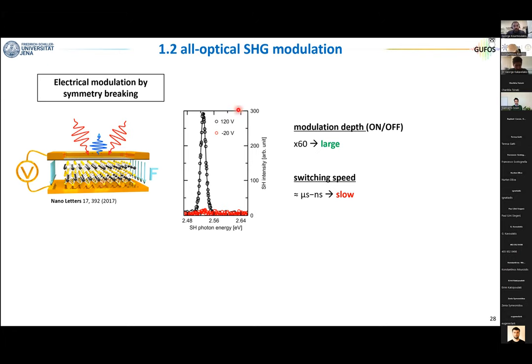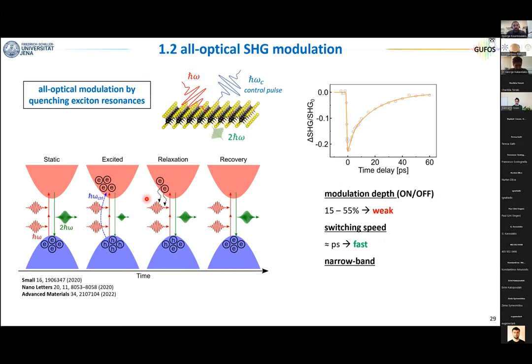So now you see that as a function of gate voltage, you have a very large tunability of the nonlinearity. The advantage is that the on-off ratio is very large. So you see this is a factor of 60. The problem is that electronics is intrinsically slow. You can never switch on and off your signal at sufficiently high speed because you will be limited by your capability of switching this electric field, that typically is at a maximum of nanoseconds. And that's why people go to the all-optical modulation.